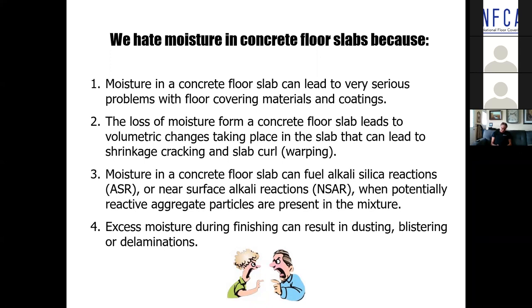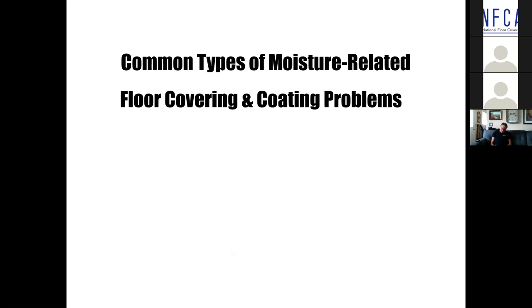Excess moisture, if you will, during finishing can result in a slab that's dusty. It can also contribute to blistering and delaminations in the slab surface. I have two schools right now down in Massachusetts where both of those schools have serious issues with delamination. I also have a 7-story hospital in Tucson, Arizona. 7 floors of lightweight concrete, all delaminated half to 3/4 inches. They've already spent $4.6 million dealing with that issue down in Tucson. So a huge issue. All right, let's take a look.